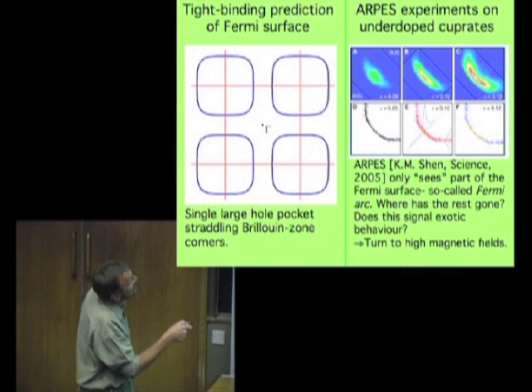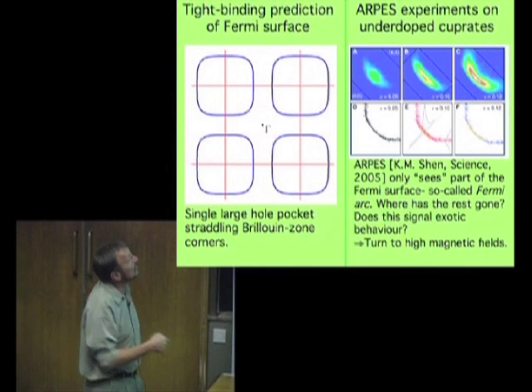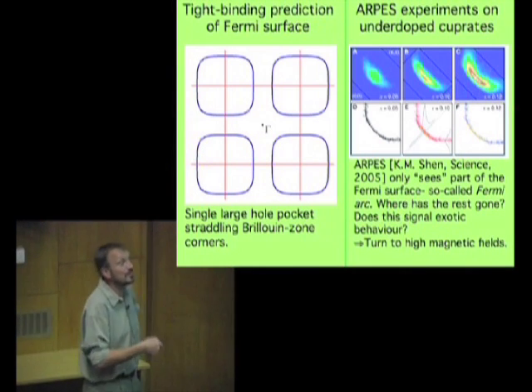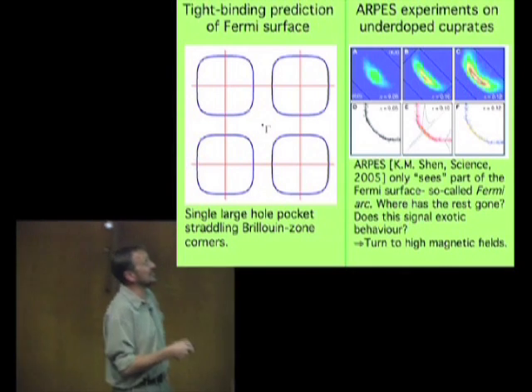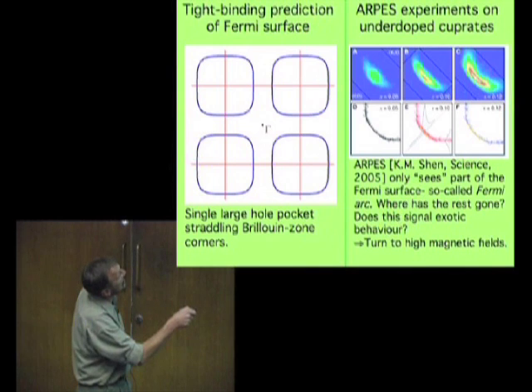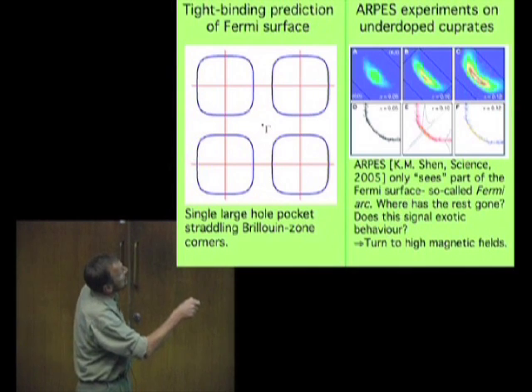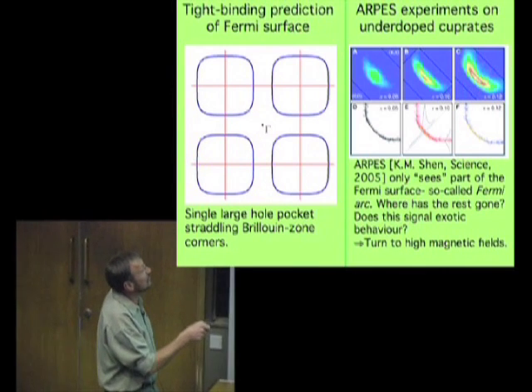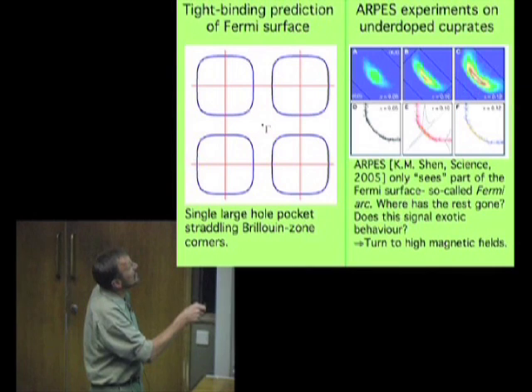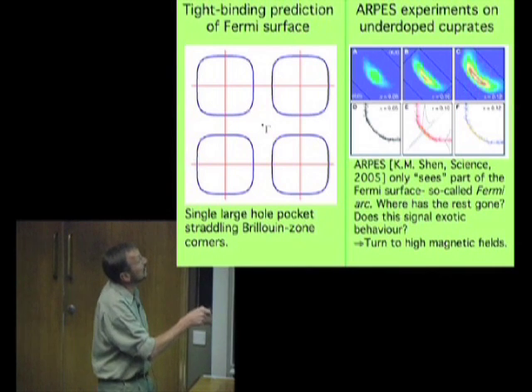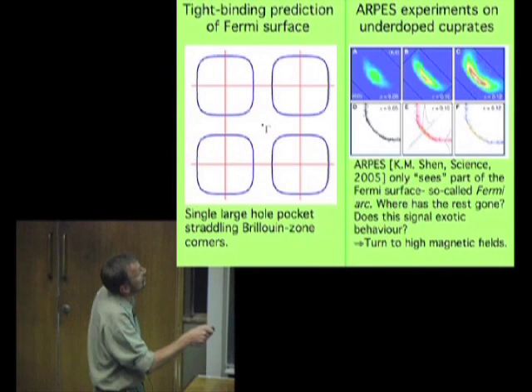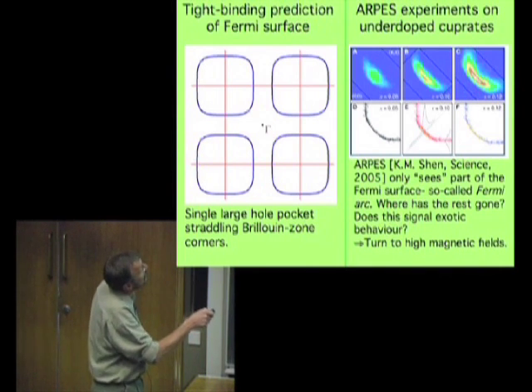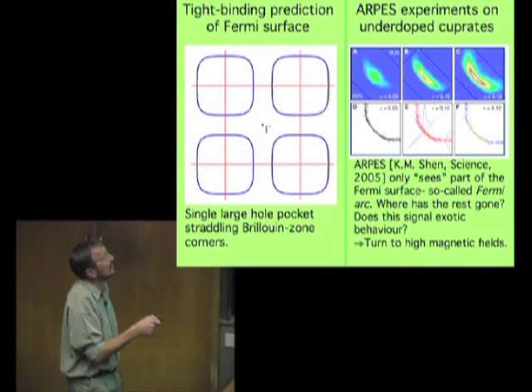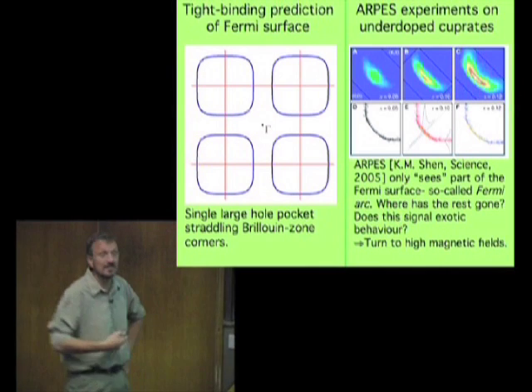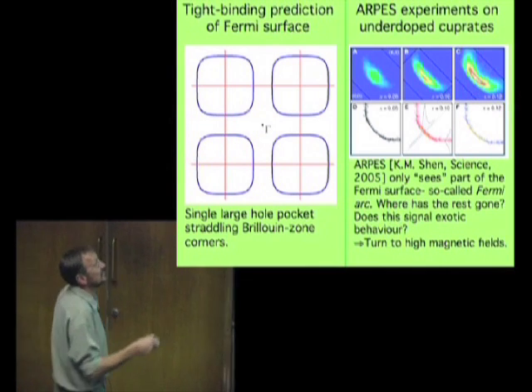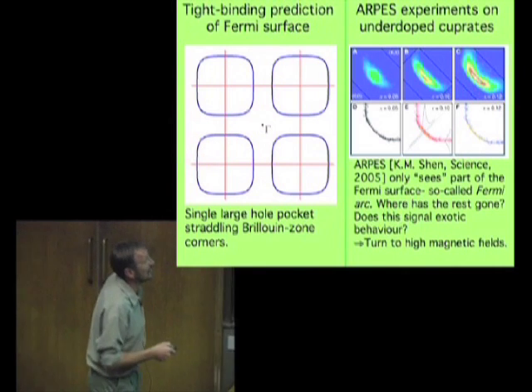So these are some mapping out paths of an ARPES experiment by Shen et al. What you would hope to see if it was a conventional metal is that there will be a big weight of emission at the Fermi energy, at the Fermi surface. So we'd expect to see a bright band of high intensity emission mapping out one of these lines here. But rather than following this path, what happens is we just get a bright emission in the middle here. This is for a hole density of 0.05 holes per unit cell. This is 0.1 per unit cell. This is 0.12 per unit cell. And you can see that we just get a bright band here on these corners. These are so-called Fermi arcs. And so this was regarded as being another signature of the exoticness of cuprates, that we didn't see the complete Fermi surface when we do an ARPES measurement.